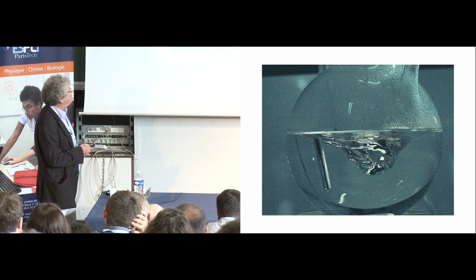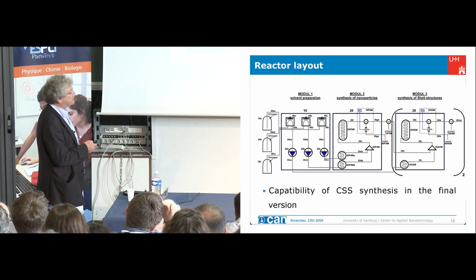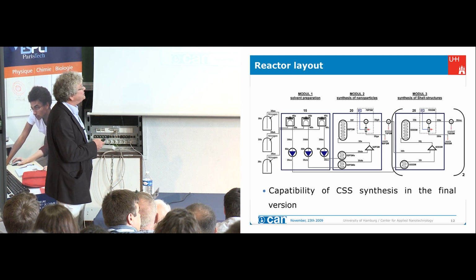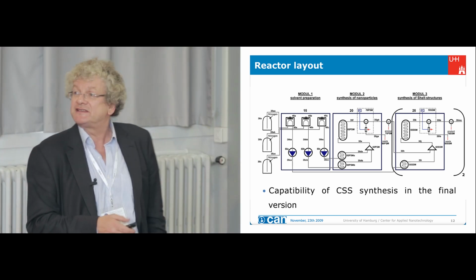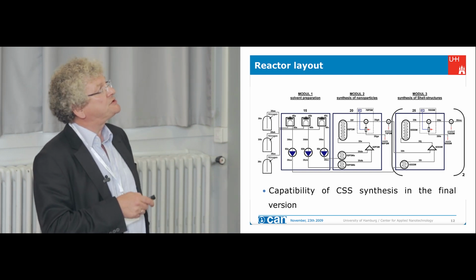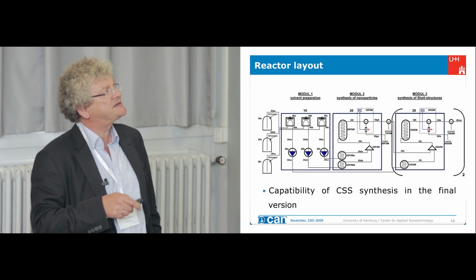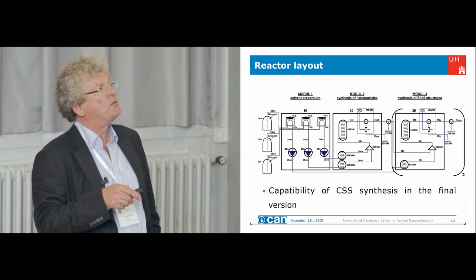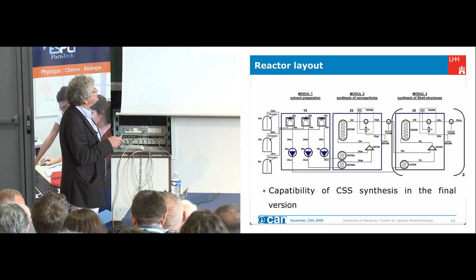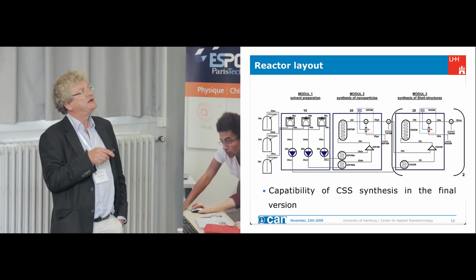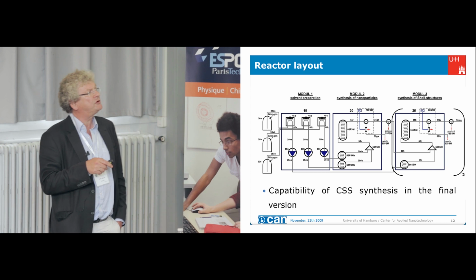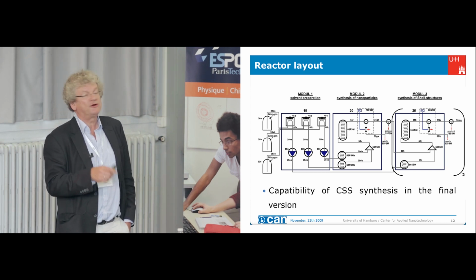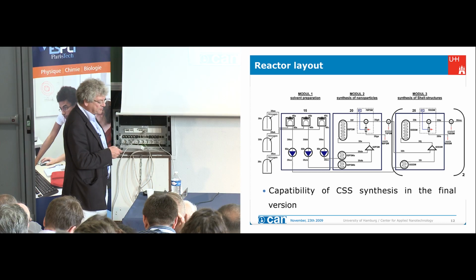So what we decided for that reason, something like a little bit more than 10 years ago, to develop a continuous flow system. Because in this case, everything is automatic. So we have precursor solutions, we have pumps, we have some degassing, we have some heating, and we have a mixing chamber where we mix these solutions. This is only for nucleation. Here we have one temperature for nucleation, a steep temperature jump here on the next to a growth oven with a growth temperature here. And then we have spectroscopic online control. We can add different modules here for growing shells on these materials, and that works quite nice.